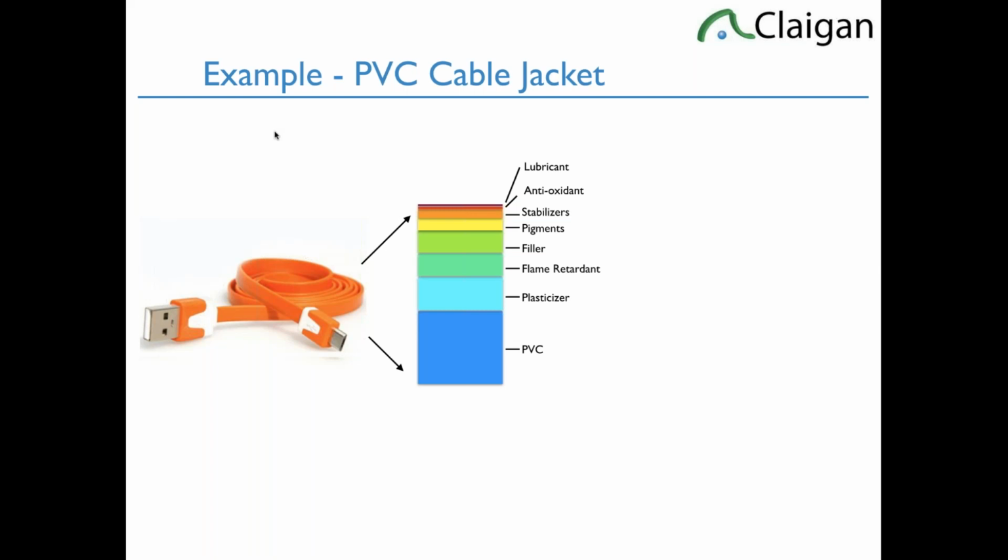The next one is a plasticizer. So you take PVC. PVC's natural state is rigid, like your water piping. To make it bend, you have to add a plasticizer. And the way they work is they basically work like a fluid. They get between the polyvinyl chloride strands and push them farther apart, an action called swelling, like you do in a sponge, you make it swell. They push the strands farther apart and reduce their bonds of attraction.